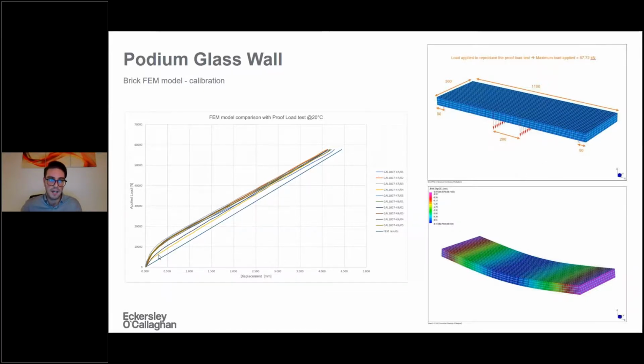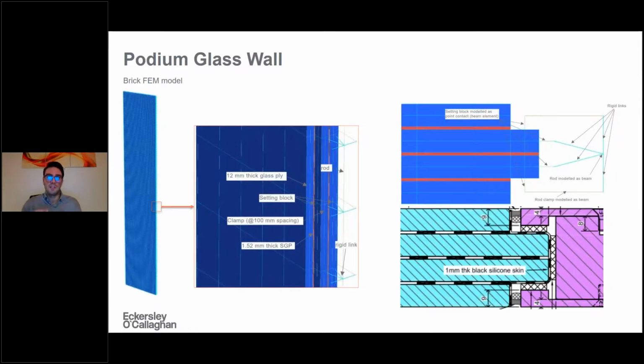And all these lines are the experimental results, basically the results from the test, and the straight blue lines are the results coming from our FEM model, which is pretty much in line with the results. So as I said, we use that basically to validate this brick model that we were requested to do, mainly to understand what was going on in this recessed area where the glass plies go from 4 to 2, to be able to engage in the clamp.